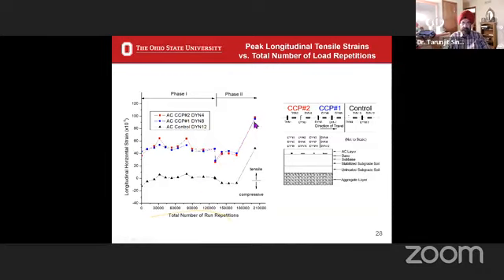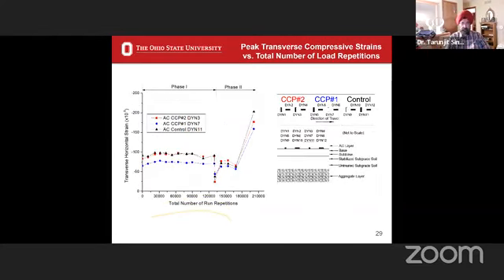Again, the two CCP sections behave very similarly and perform better than the control section. However, as soon as we began saturation and temperature cycling, they both degraded, but the CCP section still worked better. So I have several data like that. In this case, for peak transverse compressive strains, you can see that they all behave quite similarly.